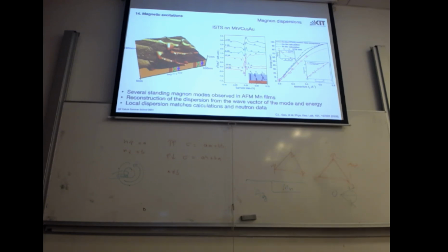And if you don't believe that, you can also see neutron data, but okay, this is manganese in FCC configuration. FCC manganese does not exist in nature. You have to force it into FCC. This can be done by doping with nickel. So we take manganese doped with 17% of nickel, and then we do neutron diffraction, and you get a black curve for the magnon structure. You see very nicely, okay, we see magnons.